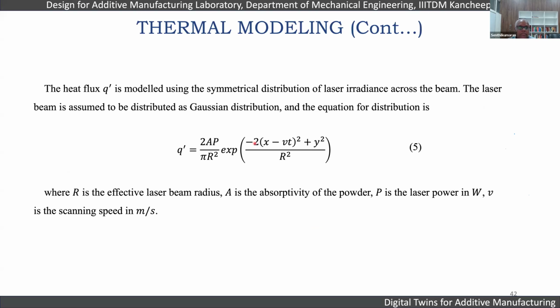Then we defined the Gaussian distribution function, as the heat source is modeled as a Gaussian heat source, and we used velocity here. For example, since it is moving along x, we used velocity along the x direction. As we increase the velocity, we move the laser along x, so x gets varied when the velocity, speed, and time get varied. So for each time step, we are able to move the laser over the path.